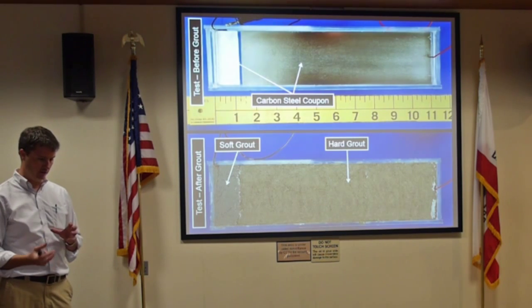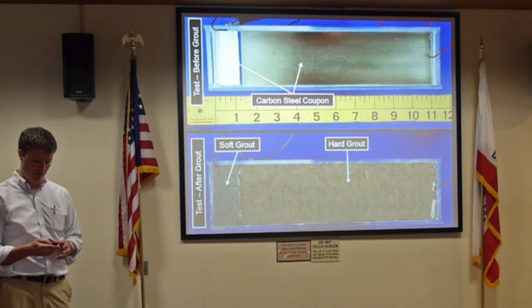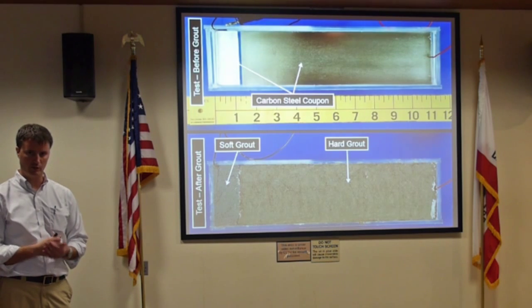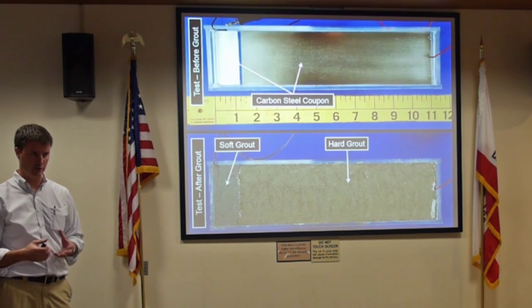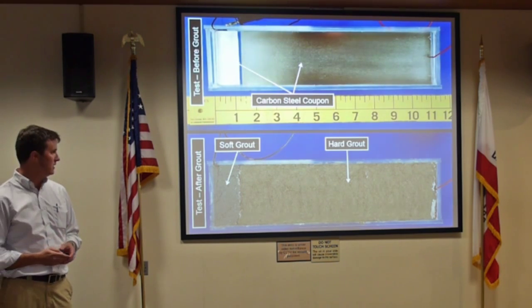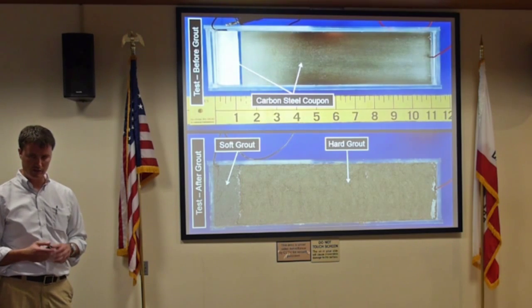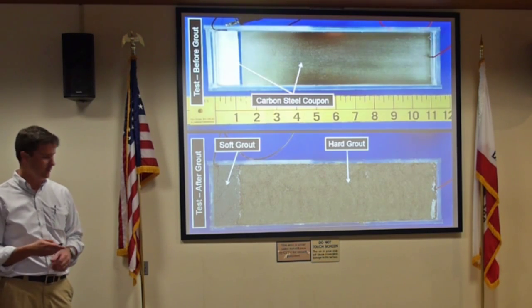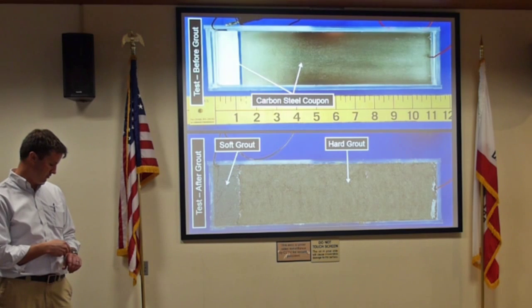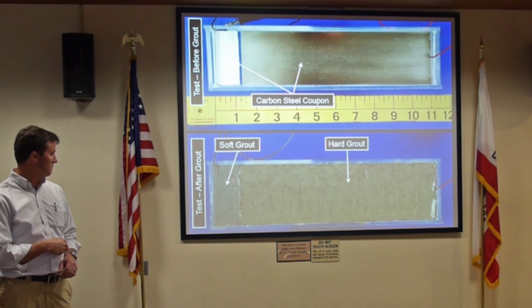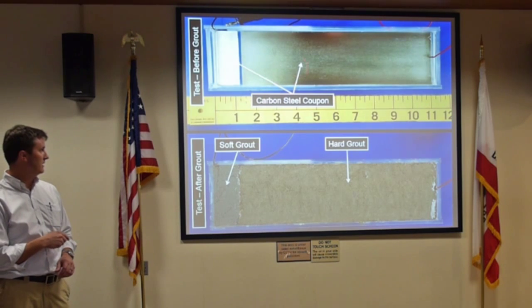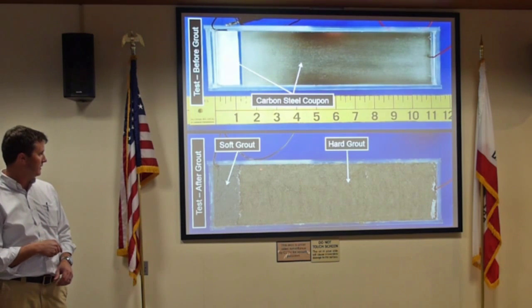We had that soft material at the top and the good material down below, and so we wanted to try to essentially recreate this environment. This essentially showed that it could drive a corrosion cell. So what we did is we took some of the material from that test sample, reconstituted it into this little bin where we took the area of steel of the suspect area, the area of steel of the good grout, and basically had hard grout, soft grout, and